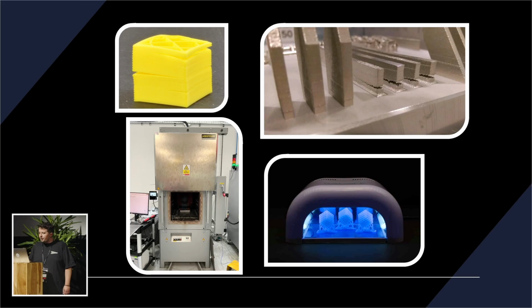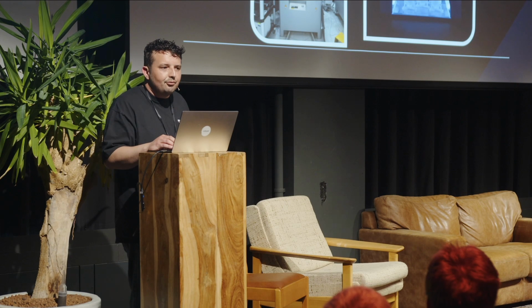Everyone's familiar with the struggle of getting a nice first layer in FDM. Well, it's a similar struggle for people working in direct metal laser sintering. If the first layer spread of metal powder is too thick, then the print will warp and peel off the substrate in much the same way the plastic does when your nozzle's too far away from the bed for your first layer. And that perfect first layer obsession, in metal AM it's called recoater blade gap optimization. And it's the same drama, just a fancier term.